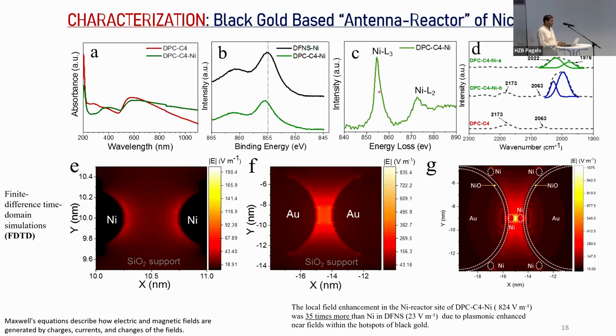But the problem with both these techniques is that when we do them, the sample gets exposed, right, whenever you do the conventional XPS or conventional EELS. So then we did this in situ CO titration, which allows you to do it in a glove box, in an inert atmosphere, and these two signals indicate that it is nickel zero based on how the CO binds. Obviously, there is some amount of nickel 2 plus, but 90% of it is nickel zero.